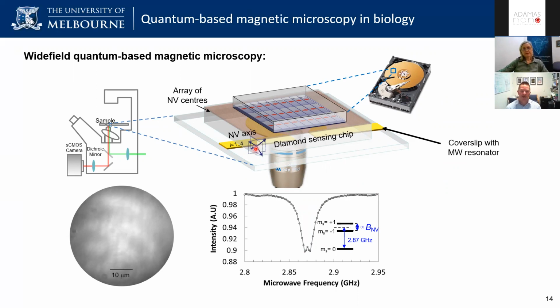Yeah, it certainly does, and it limits. Because the refractive index is 2.4, these high NA, high magnification objectives often have a very short working distance. When you're going through a higher index, that effectively shortens your working distance. If you're comparing water to diamond, it nearly halves your working distance. That is the reason why we've had to use these thin diamond substrates. We're working with substrates that are 50 to 100 microns thick. The typical working distance of these objectives is maybe 300 microns. So you've got to go through the cover slip, through the diamond, to then image this surface nicely. So we're limited to about 100 microns for these diamond chips.